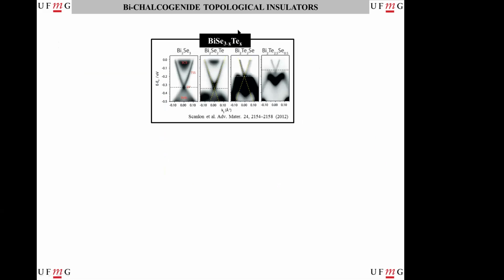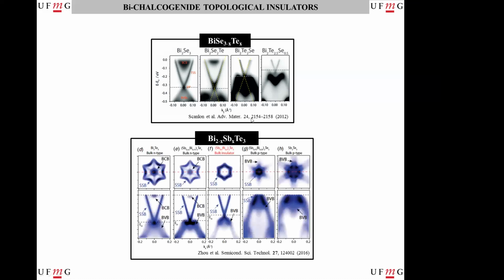We can also have a mixture of these elements, and we can have samples with three of these elements. For example, here we change the selenium and tellurium ratio in the bismuth selenide system, and here we have an ARPES image of the Dirac cone, showing what happens with the Dirac cone when we change selenium for tellurium. And we also have here an ARPES work where we change the amount of bismuth and antimony and maintain the tellurium. We can observe the changes in the surface states of bismuth telluride also.